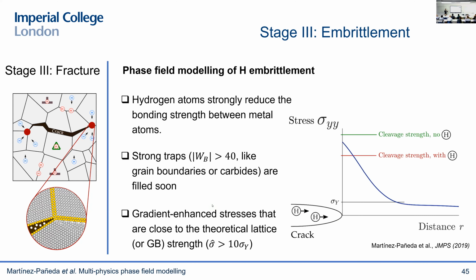Another question is, okay, if you have a 30 to 40% reduction in grain boundary strength, is this enough to observe a transition from a ductile fracture process to a brittle one? And what we have seen, and I won't get into the details, is that when you resolve the stresses over the critical distance of the problem, which requires using some higher order strain gradient plasticity, what you see is that your stresses are not high enough to reach the cleavage strength or the grain boundary strength. So that's why you need to have micro-void cracking mechanisms. But the moment you bring hydrogen into the picture, you lower this by 20 to 40%, and these two lines cross, and then you have a transition. You have a model that is naturally capable, without any ad hoc fitting parameters, of capturing that transition from ductile to brittle fracture just by simulating how much hydrogen you have and putting that DFT calculation in.